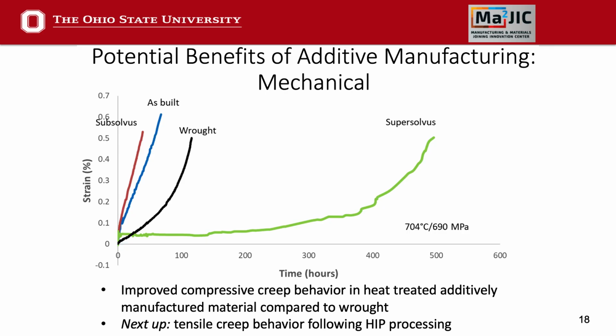Yeah, so this is great for both additive manufacturing and for qualification. In terms of additive manufacturing, if we see these superior behaviors coming from these microstructures, which you have a little bit more control over through additive manufacturing, we're seeing better behavior that opens up the application window for uses of additive manufacturing. In terms of HIP, some of the issues that still exist within use of additive manufacturing is qualification. If you're having some builds that are behaving better than others, if we're able to create a more homogeneous structure through HIP, where we see more uniform behavior, this is great in terms of part qualification.